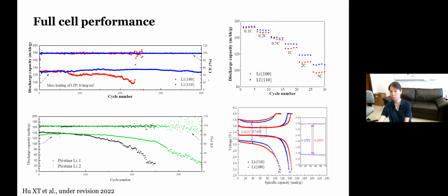Right, and how about the full cell performance? Here I show again, for the pristine lithium samples without any preferential texturing, the result varies, right? We have slightly longer-lived ones and short-lived ones, and it's always there. And in comparison with the lithium-100 and the lithium-110, you see the 110 definitely performs a lot better than the 100. We have capacity retention maintained at about 96% at the end of 400 cycles.